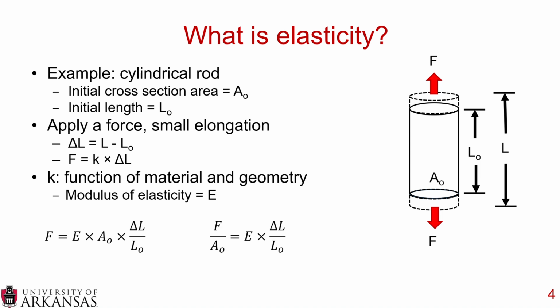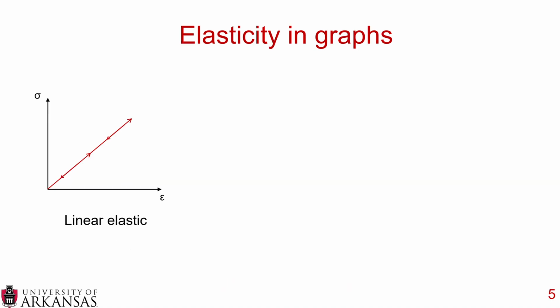And we can rearrange that equation. We can take the area over to the left side, and then you can clearly see where the stress equals E times the strain, where sigma equals E times epsilon. So this is a fundamental elasticity theory. Now we can also take a look at it in graphs. A linear elastic material is where you load something with some sort of stress. You measure the strain. When you unload it, it returns on the same path in a linear fashion. So you can just go back and forth, up and down. That's a linear elastic material.